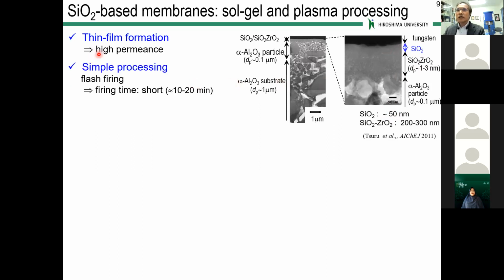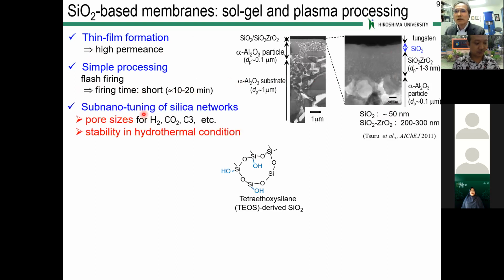And this silica-based sol-gel processing is very simple. We adopt flash firing techniques, which require a firing time of only 10 to 20 minutes for each firing step. So it is a very productive method. More importantly, the silica network can be tuned at the sub-nanometer level in terms of pore size for hydrogen or CO2 or organic gas. And we can also increase or manipulate the stability in hydrothermal conditions.